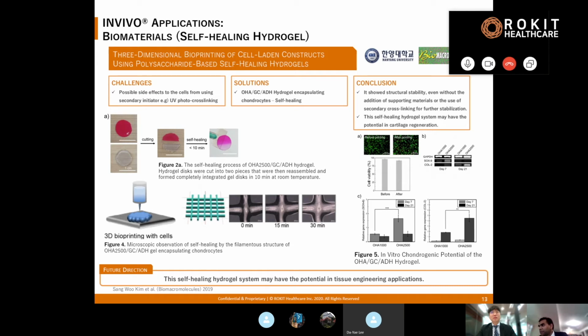The names are not important, but the point is the hydrogel that they came up with forms bonds instantaneously without post-gelation or additional cross-linking processes. And that's demonstrated here. They cut these and then they let them heal, and within less than 10 minutes, they're able to heal. And this is a very close microscopic view of that process of healing of the hydrogel.